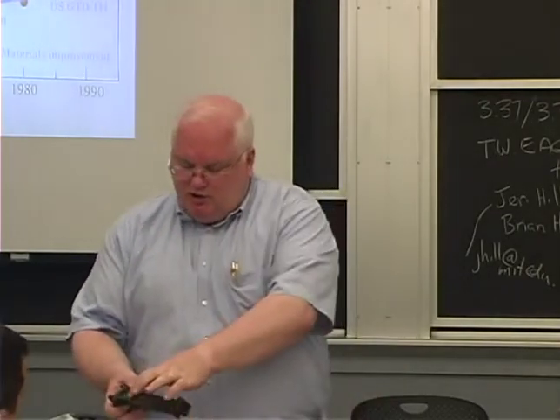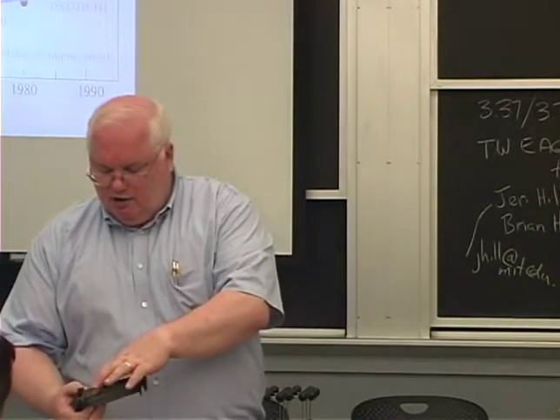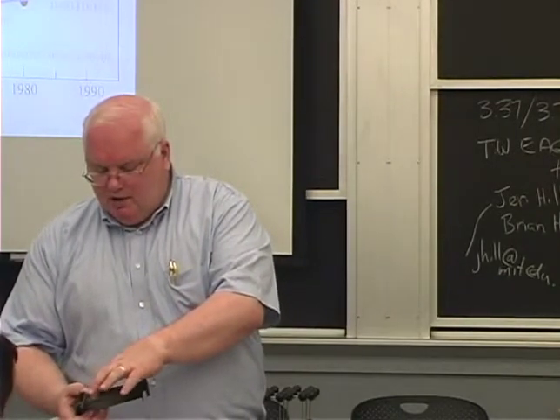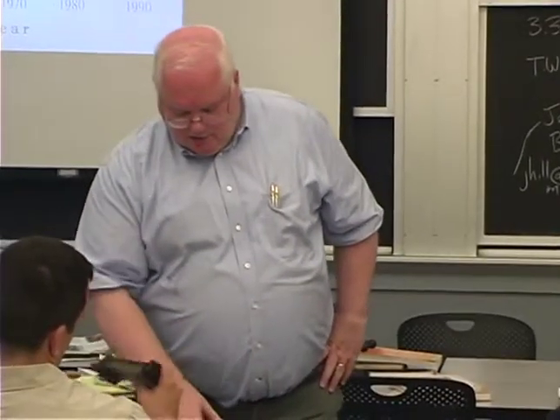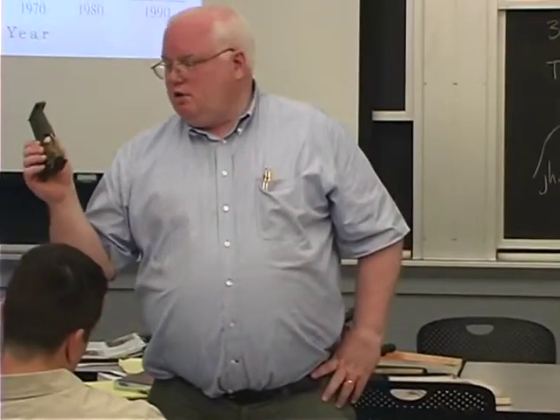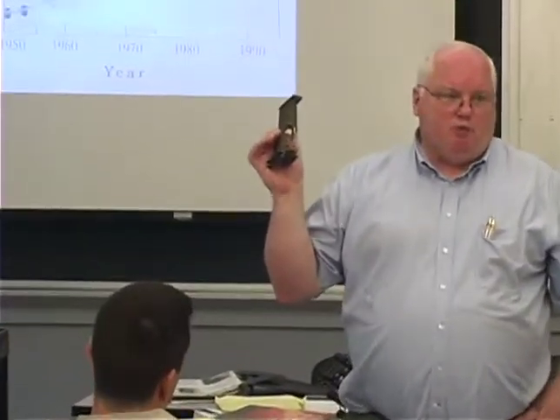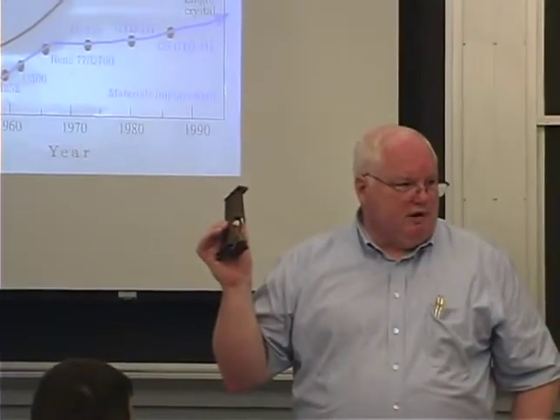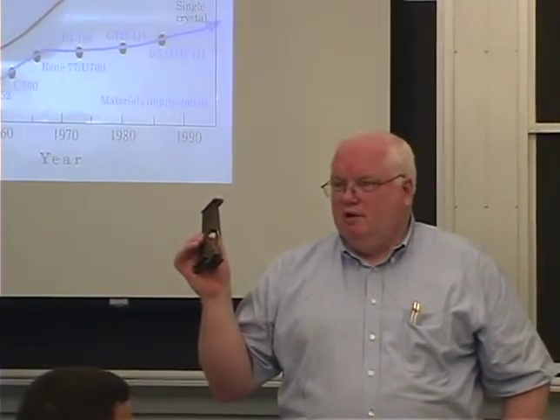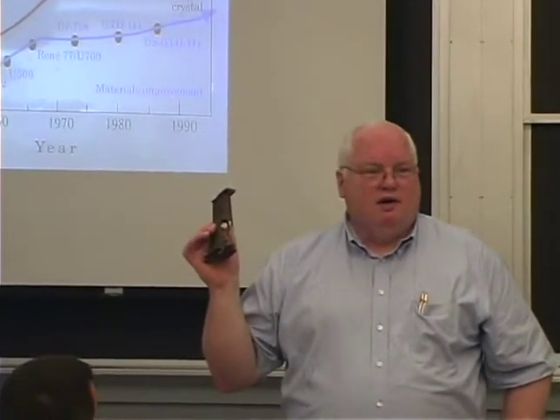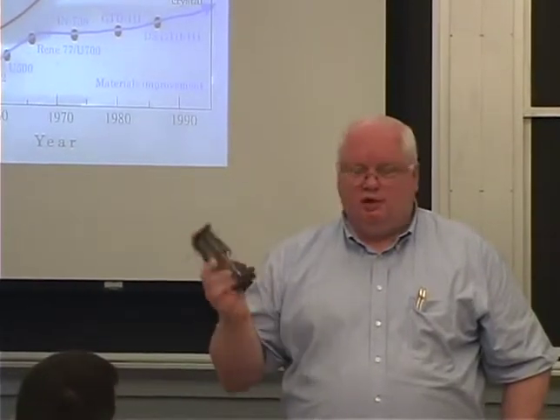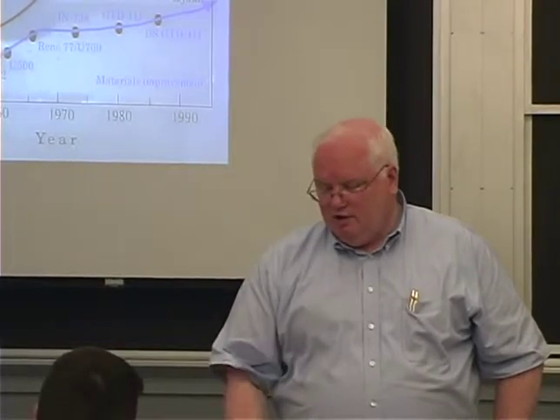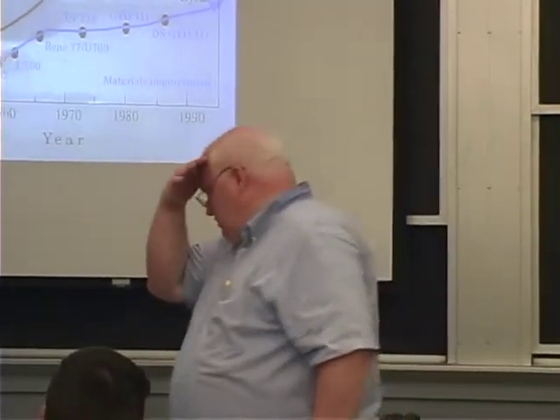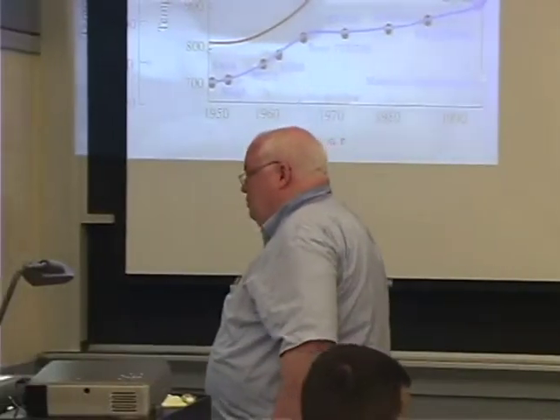That's a good blade, and you actually can see where they've coated it. This one's been repaired, and they put a coating in here. You can see the discoloration. This is one where the coating didn't work very well. This came out of an operating commercial jet, okay? And they were all like this. And if it had gone much longer, you would have lost the engine, okay? So, and it's all distorted and everything else. And that's one of the reasons they knew it was a good time to take it out. Some of the engine operation was falling behind.